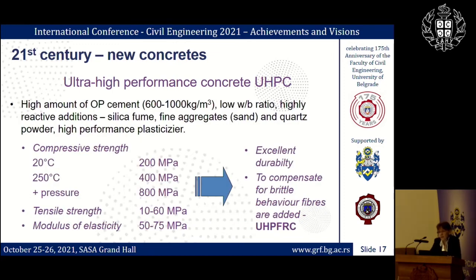This type of concrete is in fact a cement composite, which contains a large amount of ordinary Portland cement. It must have low water to binder ratio. It must have highly reactive additions such as silica fume. It has only fine aggregates, sand, with quartz powder, and of course it must have high performance plasticizers. Depending on the temperature of curing, it can reach 200, 400, 800 megapascals if you apply pressure also. Tensile strength and modulus of elasticity are also much higher than for conventional concrete. It has excellent durability, but it is a brittle material, so to compensate for brittle behavior, usually fibers are added, and that's how we get ultra-high performance fiber-reinforced concrete.